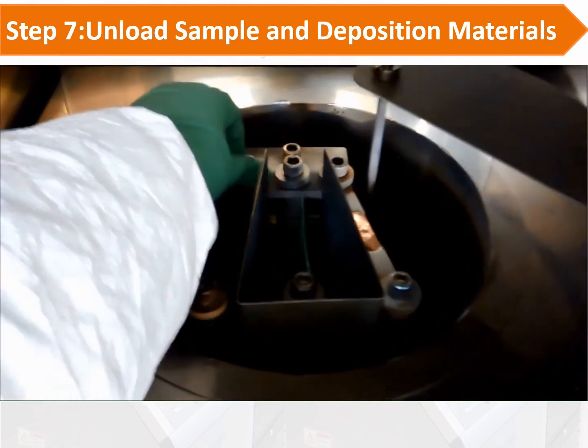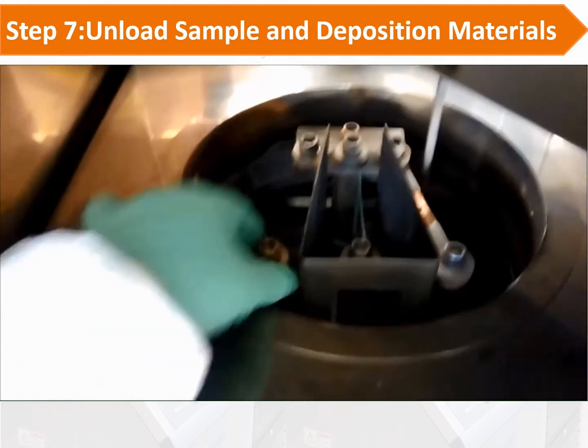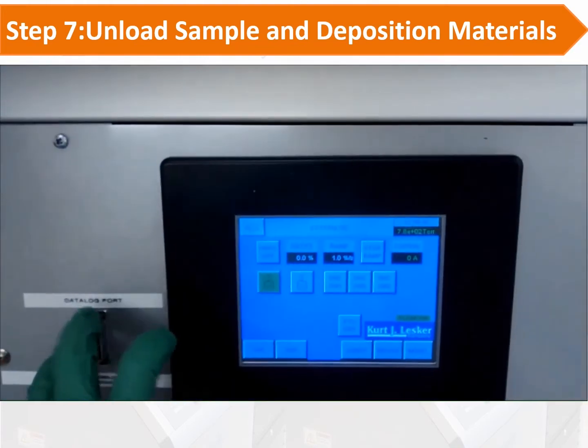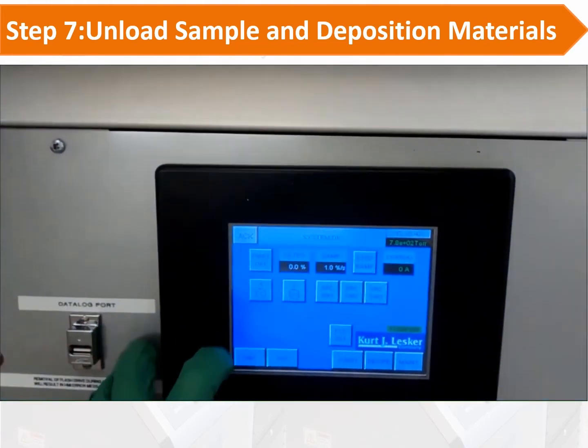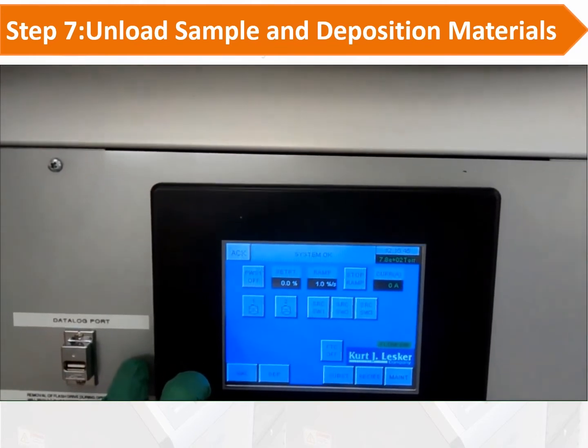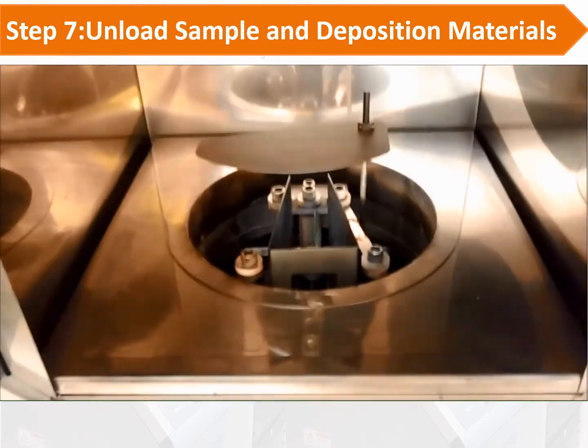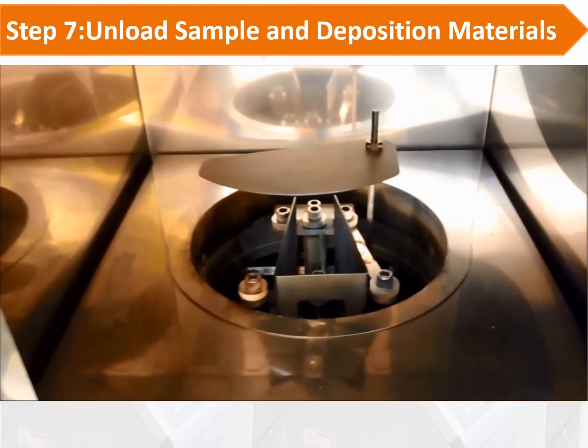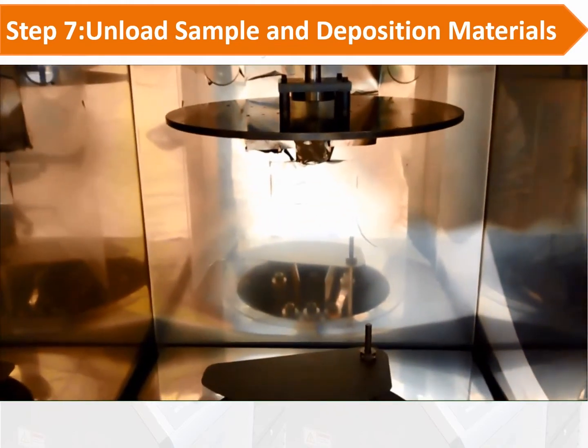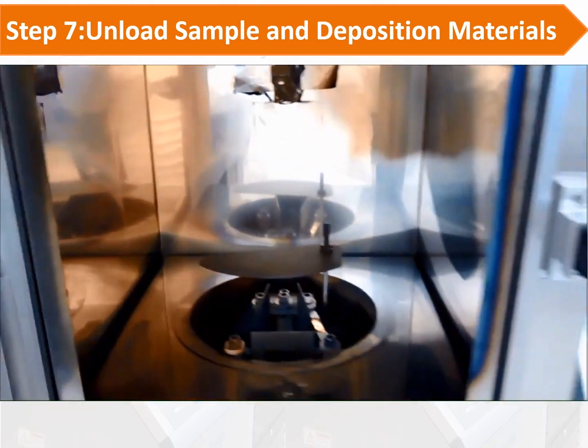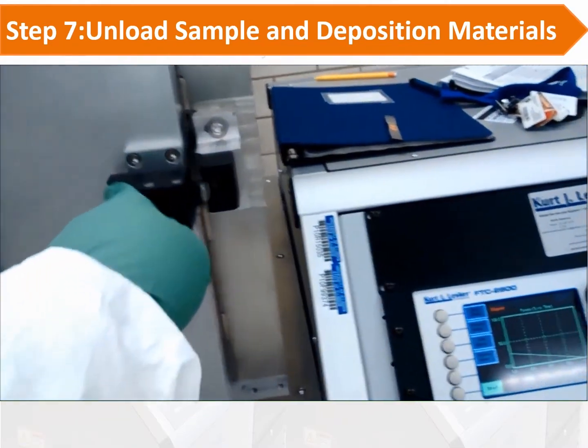And also remember to tighten the bolts after removing your gold cells. And if you unload any silver or copper boat to load your gold boat in for your deposition, remember to put the copper or the silver boat back into the chamber. And now you can manually close the shutter, and then we can carefully close and lock the chamber door.